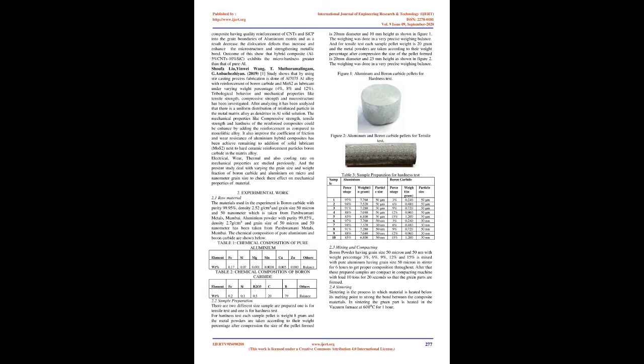Mechanical properties and microstructural characteristics are analyzed to see the effect of carbon nanotube weight percentage, 1%, 3%, and 5%, and silicon carbide particle as reinforcement. Further, field emission scanning electron microscopy, energy dispersive X-ray spectroscopy, and optical microscope are used to investigate the surface topography and microstructure. Hardness of the specimen is measured using a Vickers hardness tester. SEM and microstructure micrographs show that the sintered Al-CNT-SiC composite has quality reinforcement of CNTs and SiCp in the grain boundaries of the aluminium matrix, and as a result decreases the dislocation defects, thus enhancing the microstructure and strengthening the metallic bond. The outcome shows that the hybrid composite, Al 5% CNTs 10% SiC, exhibits micro hardness greater than that of pure Al.